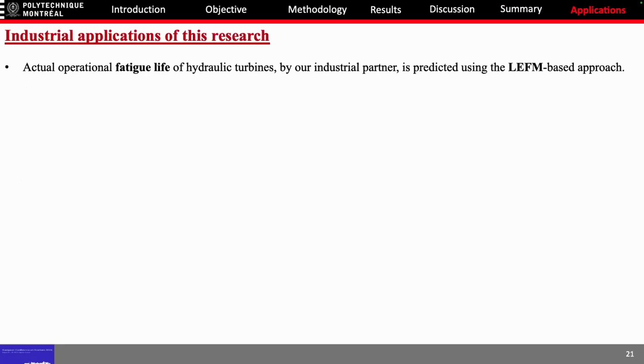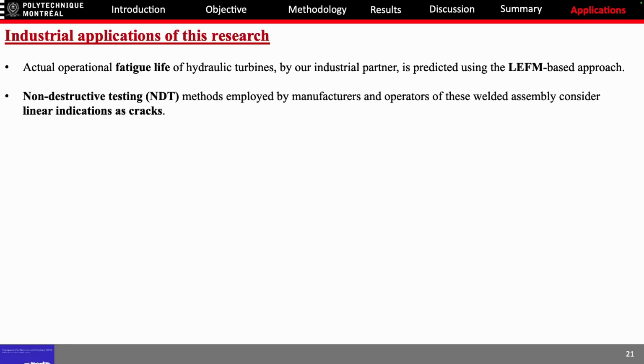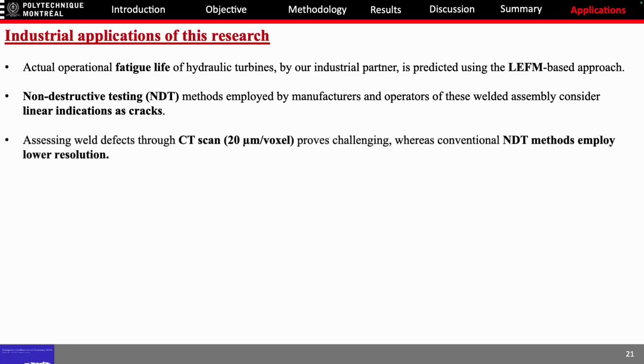So, industrial application of this research. The actual operational fatigue life of hydraulic turbines by our industrial partner, Hydro-Québec, is predicted using the LEFM-based approach. Non-destructive testing methods employed by manufacturers and operators of these welded assemblies consider linear indications as cracks, and assessing weld defects through CT scan with a maximum resolution of 20 microns per voxel proves challenging, whereas conventional NDT methods employ lower resolution.